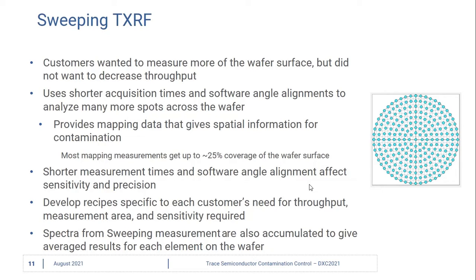Before, we were only sampling maybe one percent of the wafer surface measuring three to five points on a 12-inch wafer, but now mapping measurements can get up to 25 percent wafer coverage. These shorter measurement times do affect our sensitivity and precision, but we can work with each of our customers to develop recipes specific to their needs for throughput, measurement area,